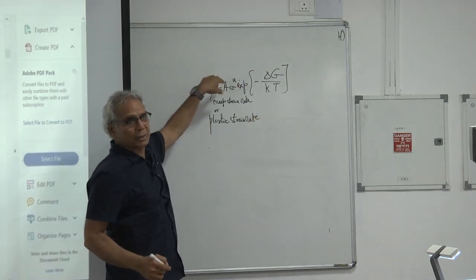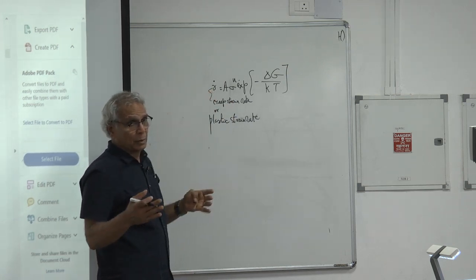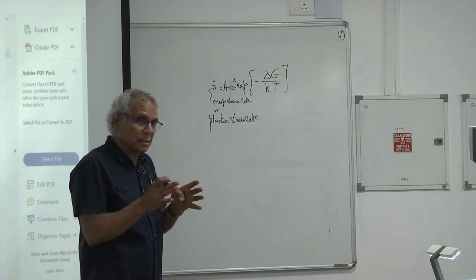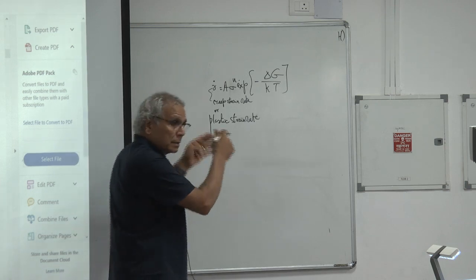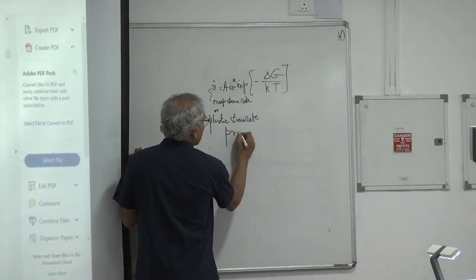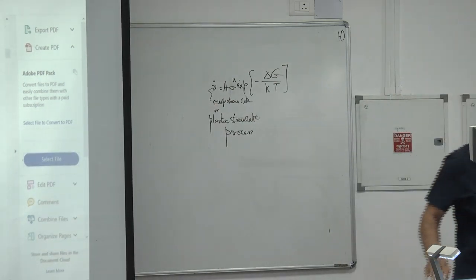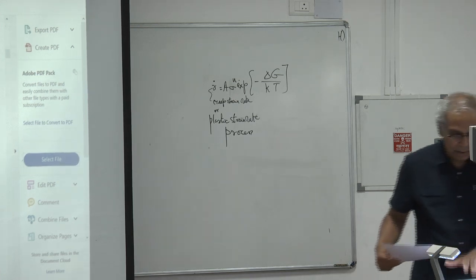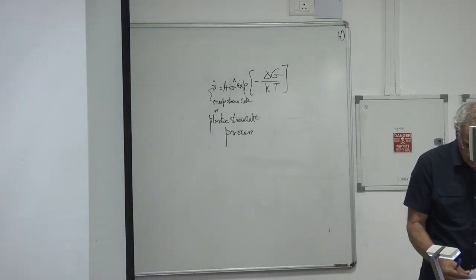This is a process, right? Because the strain is changing as a function of time, so there is a process by which it happens. So the process can be controlled by, let me put this on a piece of paper, because this looks like it's important. If I write it on the board, we lose it. Here is your thing: epsilon dot, or gamma dot, is equal to some constant, the stress on the specimen, exponential delta G over KT. This is your Boltzmann's constant, K sub B T.